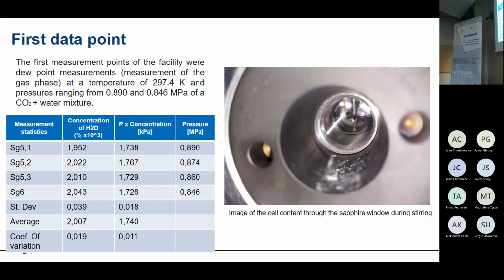The first measurement points of the facility were dew point measurements of the gas phase at a temperature of 24 degrees, and the pressure was around 9 bars. We had very good results. The standard deviation is really low, so it is very promising for the next measurements. And here you can see the image of the cell content through the sapphire window during stirring. Here is the gas phase, and here is the liquid phase, CO2 and water. So we have the VLE.